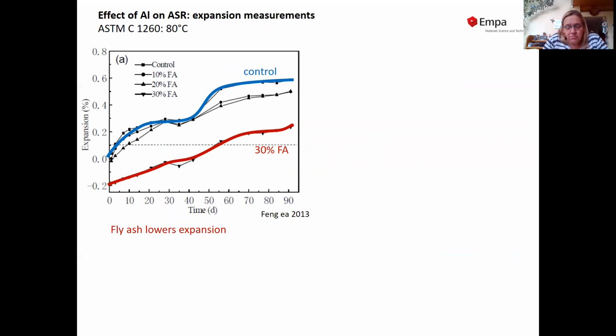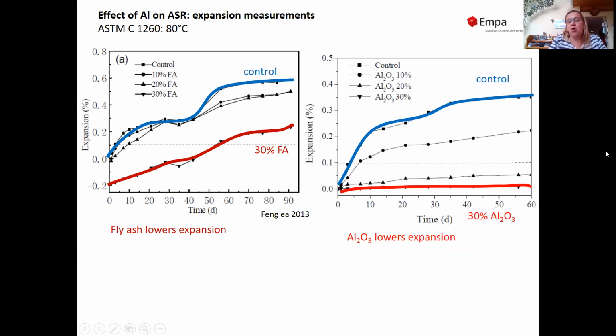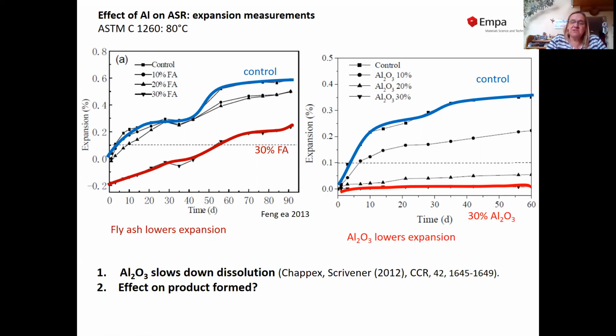If we add aluminium or fly ash to such a concrete, we normally see a much lower expansion as a function of time, as shown here, control, and in red, the effect of fly ash, or in this example, the effect of aluminium oxide, which is even able to completely suppress the expansion. Now the question is why? One of the reasons is that we know that aluminium slows down the dissolution of the aggregate, so we have a slower reaction. But this doesn't explain why we have a complete suppression.